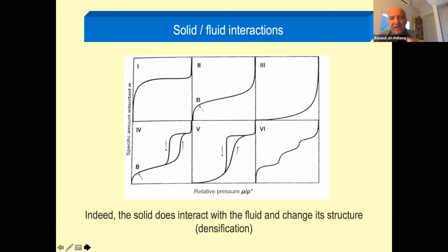That wavy one is a bit like plot number 2, but when the surface is so well organized with no defect, no cracks, no lacunae, no dislocation, nothing, the fluid can actually pile up in a very defined layer structure. That has been observed, for instance, for methane on magnesium oxide surface. Argon on graphite will do the same. You need a super well-defined surface, and then you start piling up, and every step corresponds to a 1 atomic size layer of the fluid.